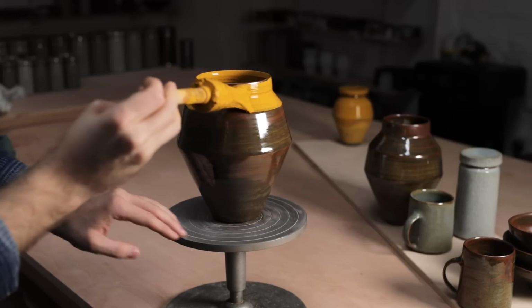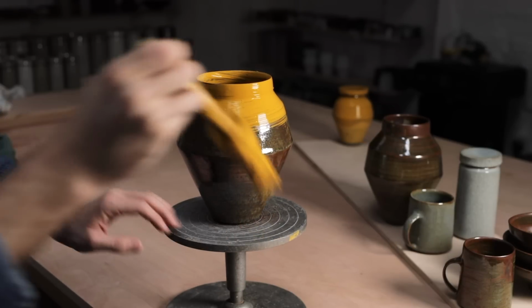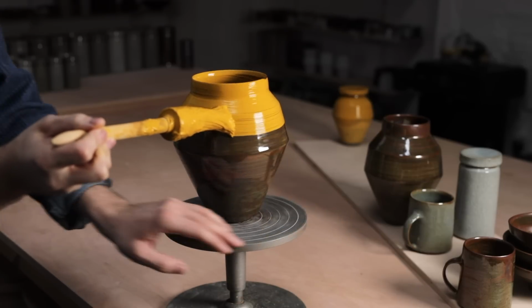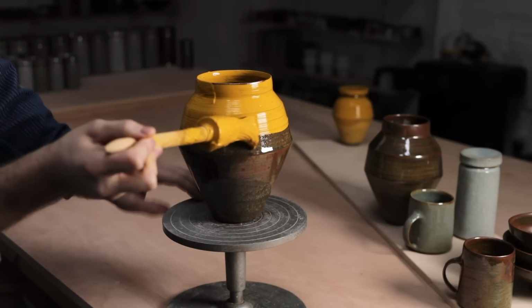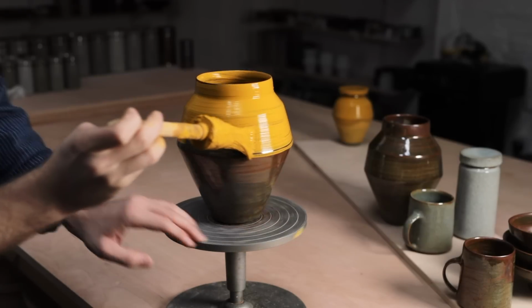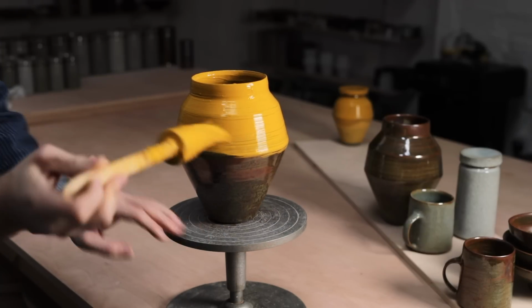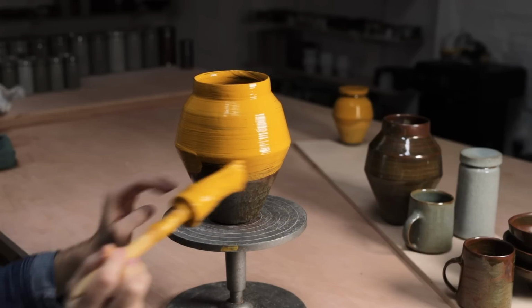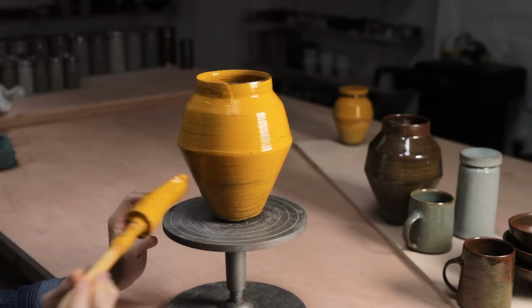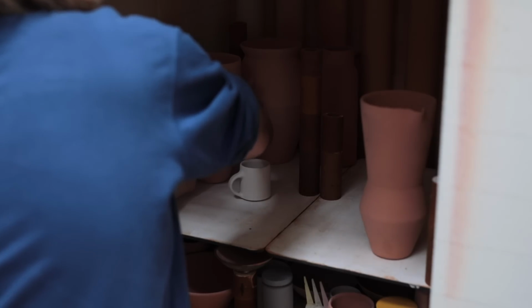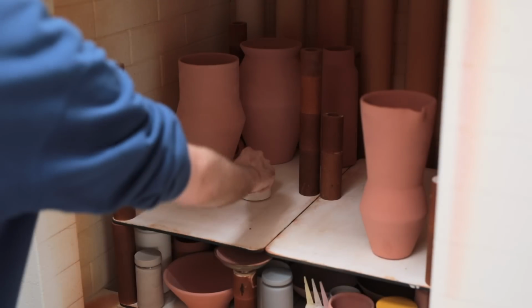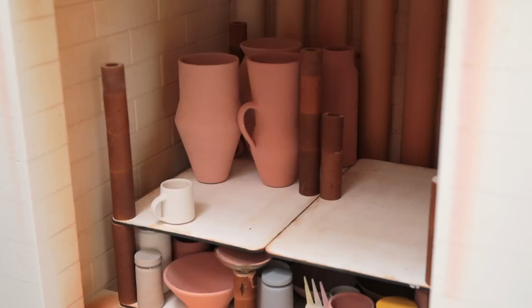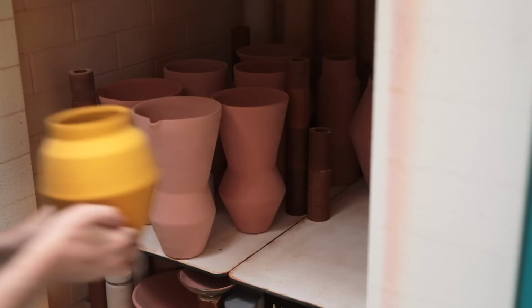There's a point where if this is brushed on too thickly, it'll begin to crack and flake off, which can happen during the firing, littering the work around it with shards of molten iron. So if, when this dries, I see patches beginning to crack and fall off, I'll simply wash the iron away, wait for the pot to dry, and then do this process again. And once again, this firing is a few months later, and I had an awkward spot in a layer of much taller work which I needed to fill, as it's much easier to achieve a good reduction when these kilns are densely packed, as there's simply less space for oxygen to occupy. And here we go for firing number 3.